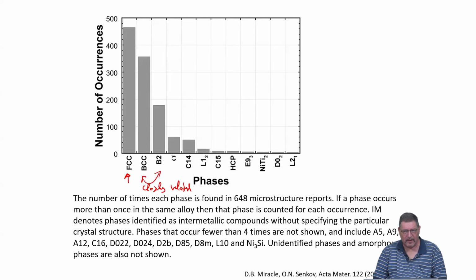So this is not related to the fact that FCC or BCC, this is my opinion, have special structures, but because the elements which we use in order to make these solid solutions, where we have to find elements which have similar properties, are favoring FCC or BCC structures. And this is, I think, why we see these phases in abundance. So there is no magic about these structures, FCC or BCC. It's just what people in the literature call structure in, structure out approach.